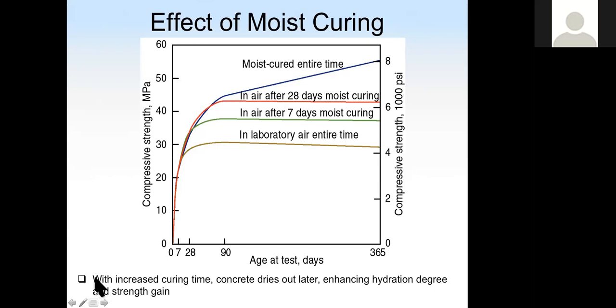Right. And here shows the curing time and its effect on the strength of concrete. For all four concretes, the mix design is the same. The only difference is how much time we put the concrete under moisture curing. When we put the concrete in air the entire time, which means after we demold the concrete there is no moisture curing, then the strength will stop going higher at early age, and the final strength will also be lower. The longer we keep the concrete in moisture curing, the more the strength will keep going up.